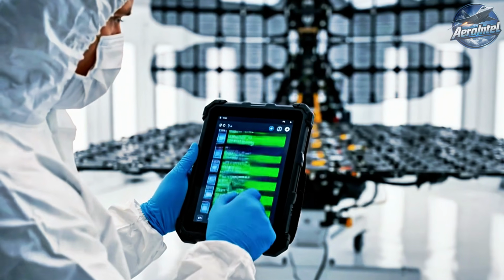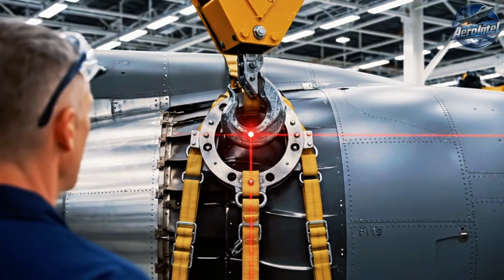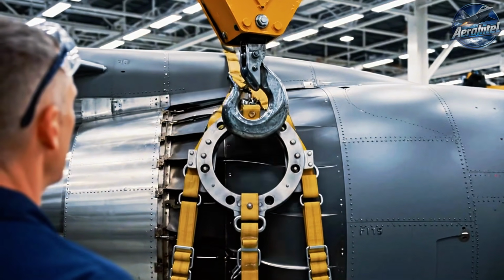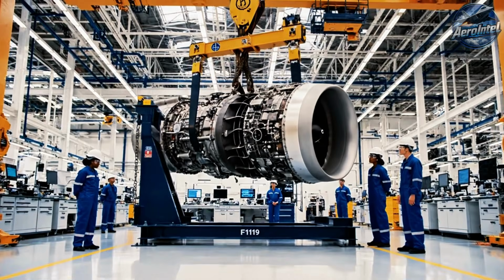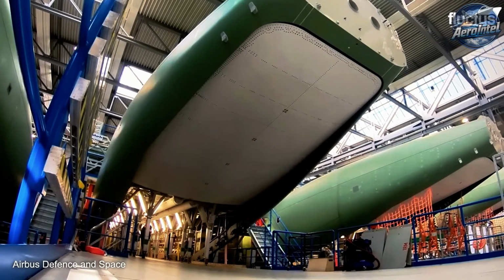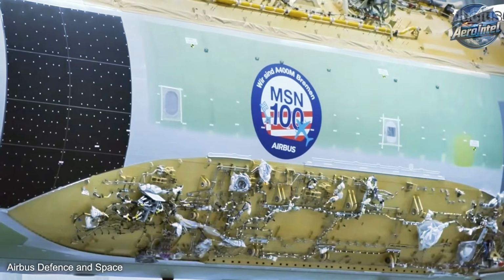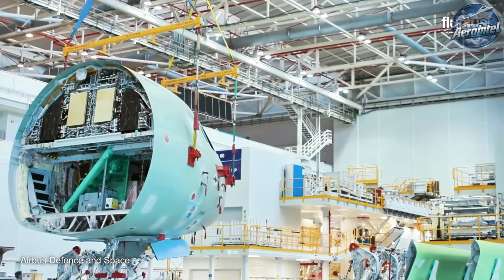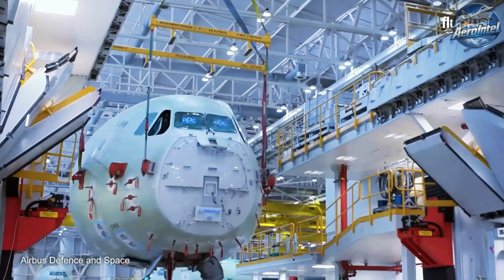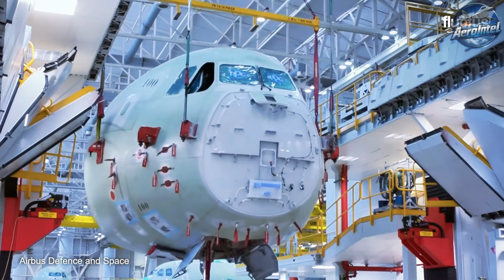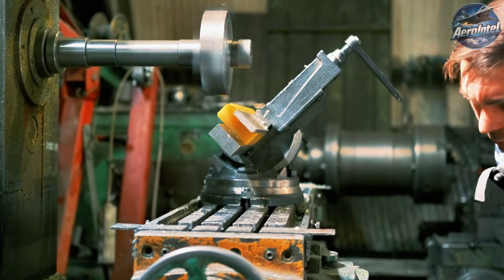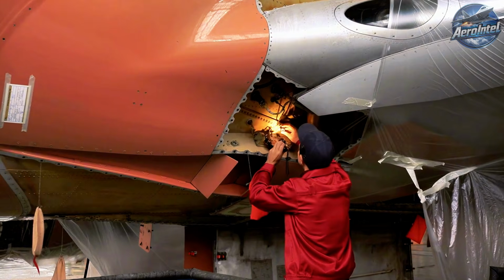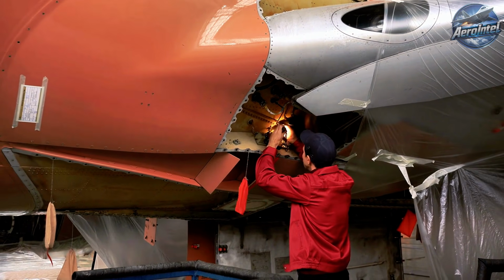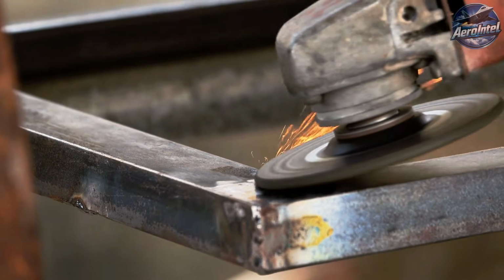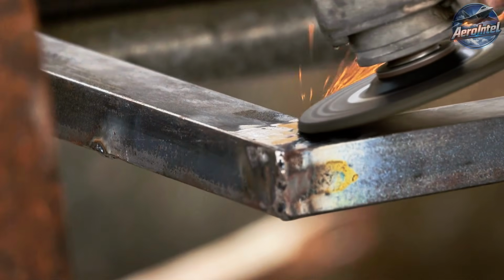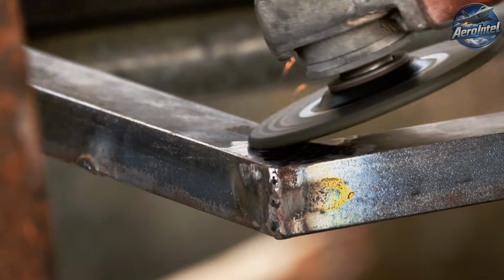Friction stir welding uses a rotating tool to plasticize the material below its melting point and literally stir the two pieces together. Because the metal never actually melts, the grain structure disruption is minimal. The heat-affected zone is tiny, and the resulting joint strength can be comparable to or better than the base material, even in aluminum. Friction stir welding is already used in parts of modern aircraft, including sections of the F-22's wing structure and the Space Shuttle's external tank, and its use is gradually expanding across the aerospace industry.